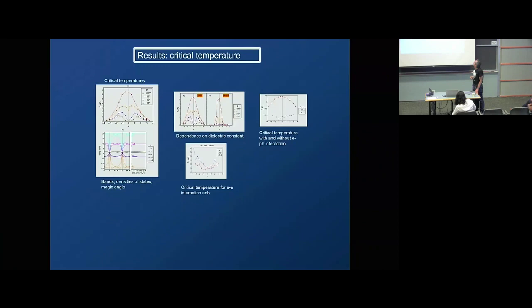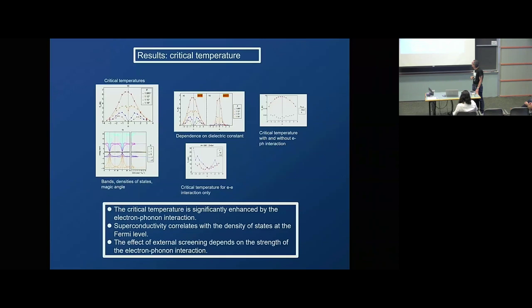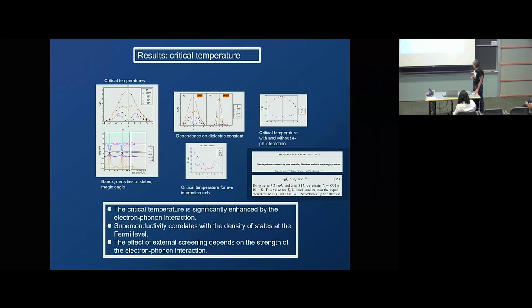And these are more results. There is a peak always in these results at zero filling. That's because we were not doing a self-consistent Hartree-Fock calculation at the time, because otherwise that peak will disappear since the Hartree-Fock will open it up. But typically the superconductivity correlates well with the electron density at the Fermi level.